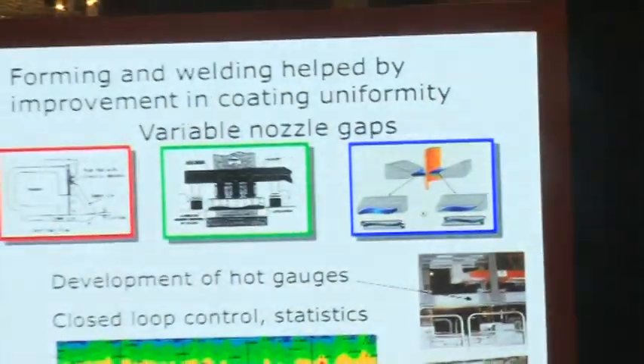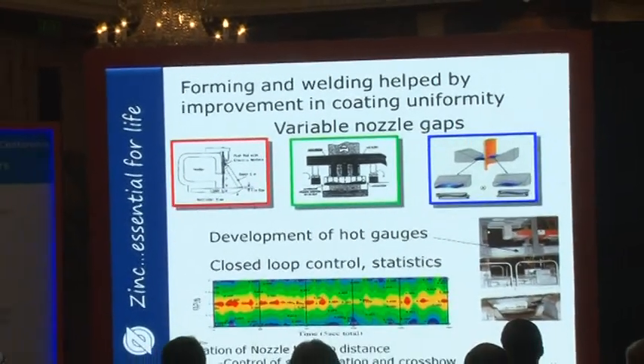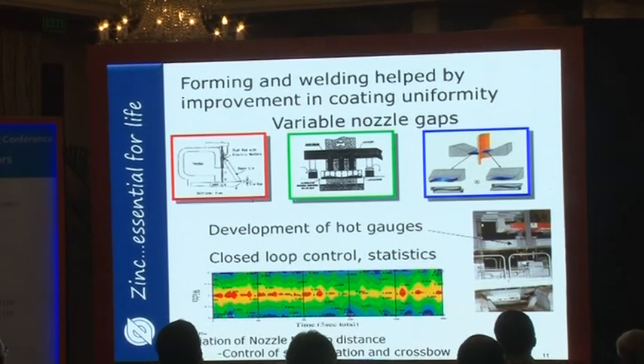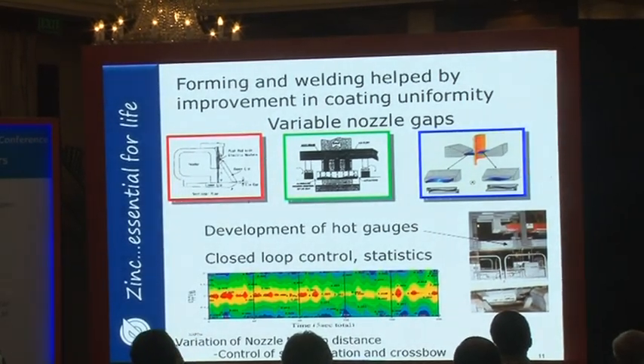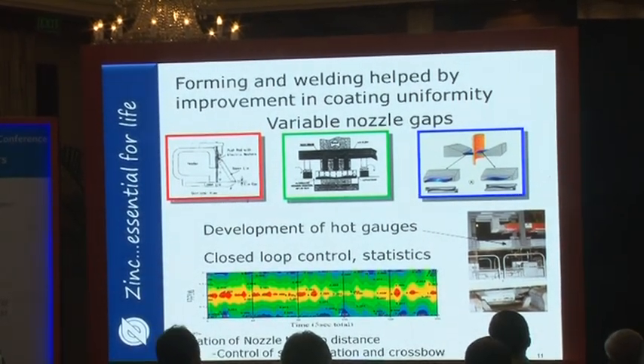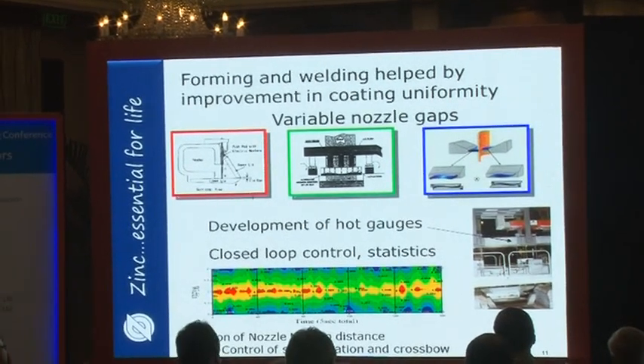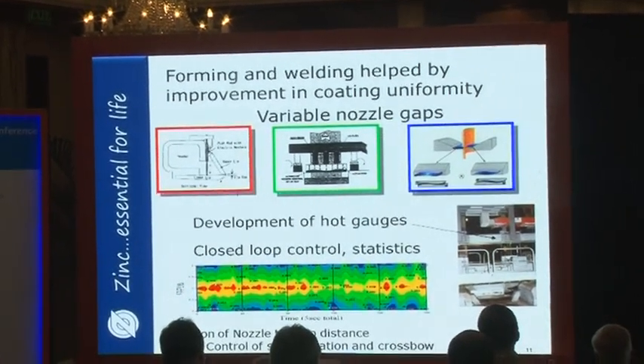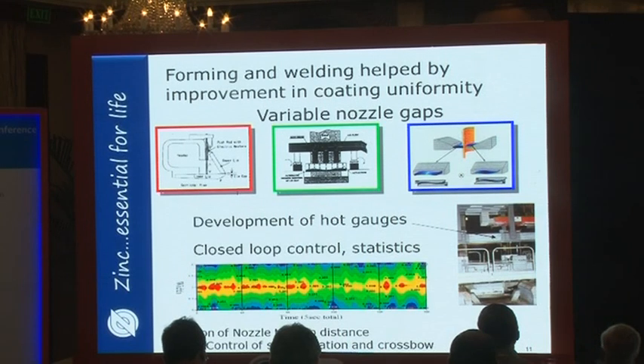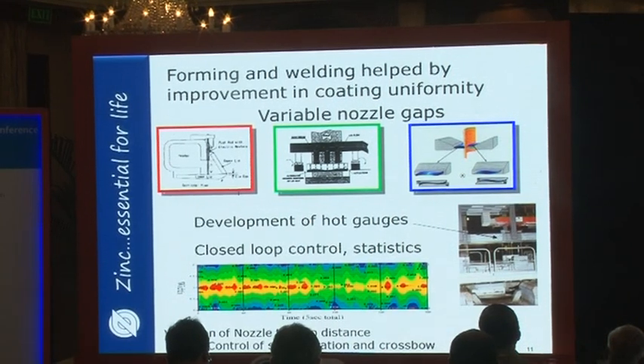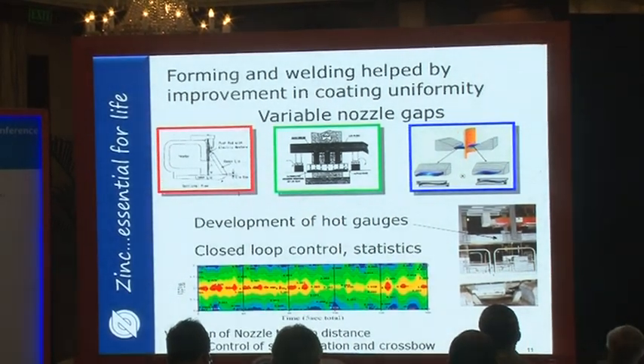So we also needed to improve the coating weight uniformity, because it was very common in the old days, and still with many of the older lines, the vibration in the line and the variation in the coating thickness. This made it very difficult for the automaker to consistently form the steels. If the coating weight was variable, then he'd have thick coating in one location and thin in another.